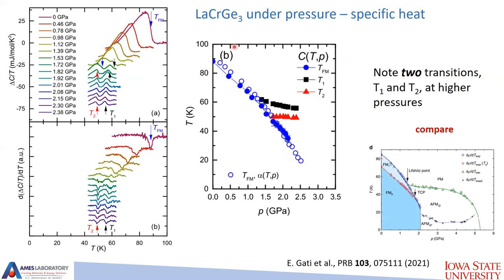So, specific heat. The ferromagnetic transition goes down under pressure. And then there are two very clear features that barely change with pressure. Here is the phase diagram, a part of it, based on specific heat. If you compare to the previous phase diagram, you will see that this part is basically the same as before minus this crossover line. However, here there are very clear signatures of two transitions as opposed to one down there.